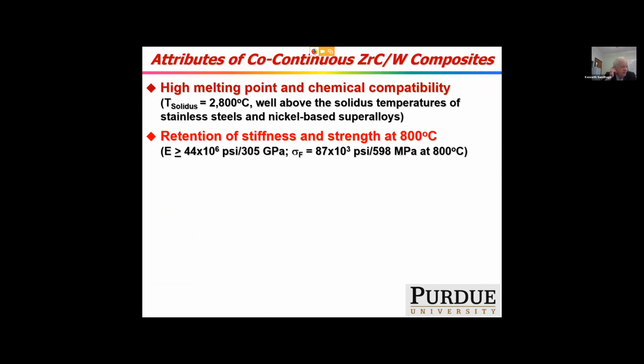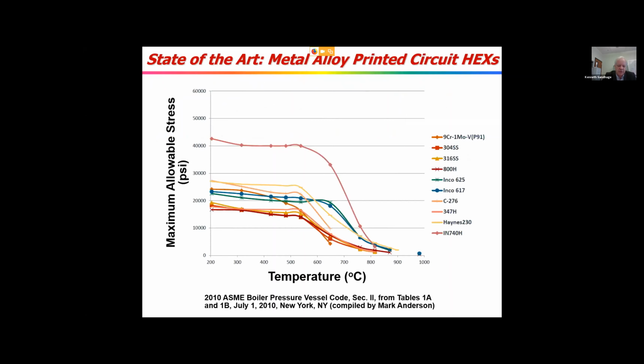So just to remind you, even for this application, ZrC-tungsten has attractive characteristics. Again, it's high melting, well above the solidus temperatures of stainless steels and nickel-based superalloys, which are typically 1300 to 1400 C or so. They're stiffer and stronger at 800 C. And so as you'll see, we measured the failure strength of these materials at 800 C, and it's about 87,000 PSI. And so just to put that in perspective, here's again the ASME boiler pressure vessel code.